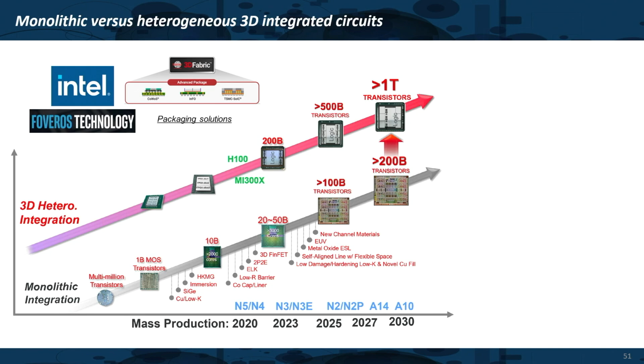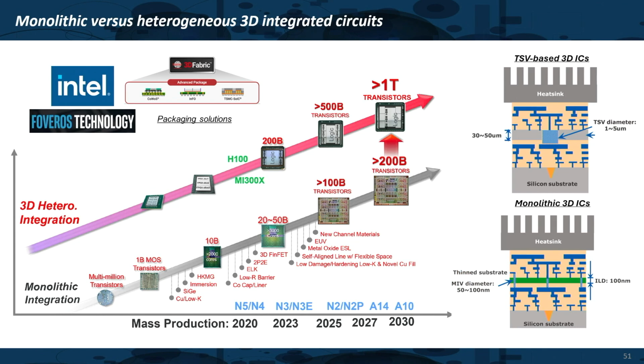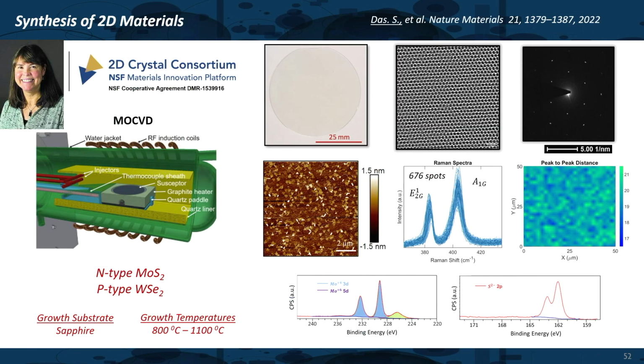Although industry is looking into a different way of doing this heterogeneous integration using packaging technology, they're putting different chiplets together using an interposer. But eventually, to have the highest density of interconnection, you have to go monolithic 3D integration, because when you do through silicon vias, the via dimension can only be tens of micrometers, maybe down to a micrometer. But when you do it in a monolithic manner, you can have vias as small as your transistor interconnects. And that's why monolithic integration is the best way of getting the highest transistor interconnectivity, which is the key for 3D integration. So this is something that we are doing at Penn State.